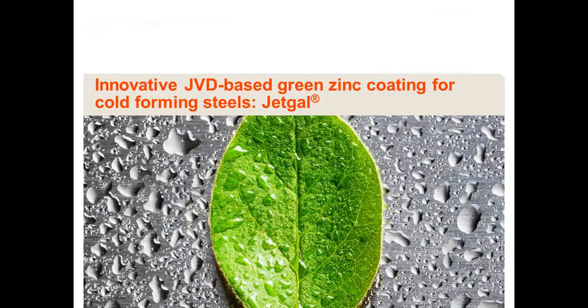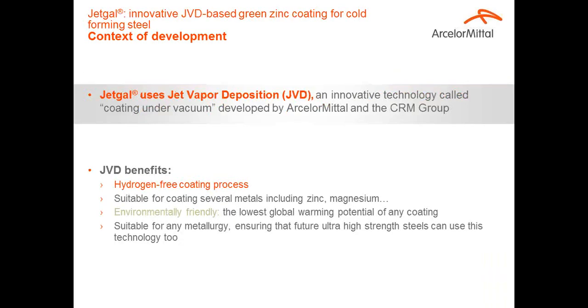So now let's discuss another pure zinc coating, but applied in a new way, and which is called JetGal. JetGal is a pure zinc coating using the new technology, jet vapor deposition, which is in fact a technology of coating under vacuum, which has been developed by ArcelorMittal together with CRM Group. So what are the benefits of jet vapor deposition? First, it is a hydrogen-free coating process. In fact, the coating step is made under vacuum, so we have no contact with water, air, hydrogen, oxygen. So it's a vacuum process.